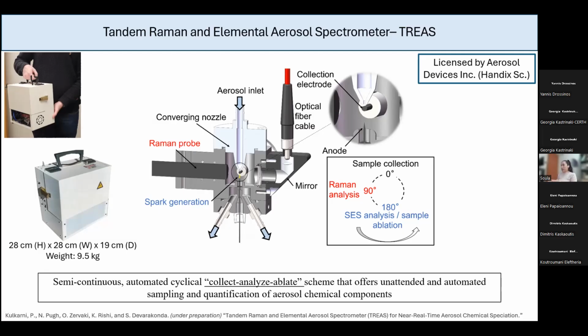After the collection is completed, the electrode rotates by 90 degrees, where it faces a Raman probe. After the Raman spectra are acquired, then the electrode rotates again by another 90 degrees, where the sample now faces a sharp electrode. The sharp electrode and the collection electrode form, when you apply high voltage, a spark generation that's burning the sample, and the radiation that is emitted is then being collected by an optical fiber cable, which can give you elemental identification of the composition of the sample.